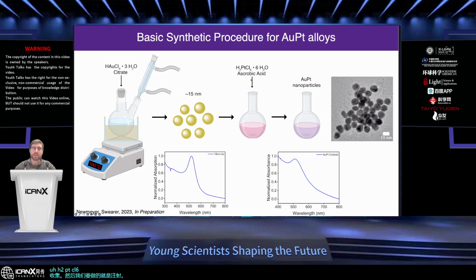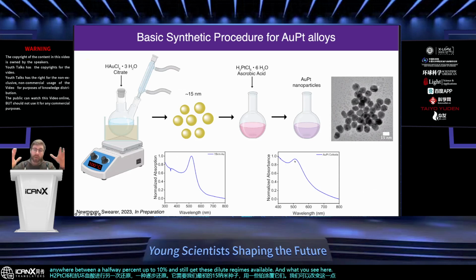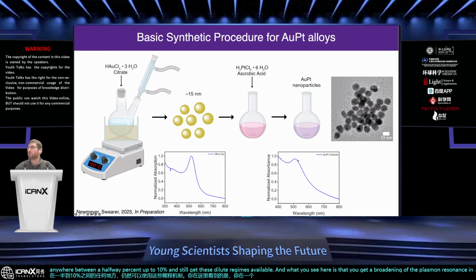H2PtCl6 and ascorbic acid to do another reduction, kind of a stepwise reduction. It takes our initial 15 nanometer seeds and coats them with some amount of platinum. We can vary this anywhere between 0.5% up to 10% and still get these dilute regimes available. And what you see here is that you get a broadening of the plasmon resonance and a slight damping, but you still maintain some of those strong absorption features overall.